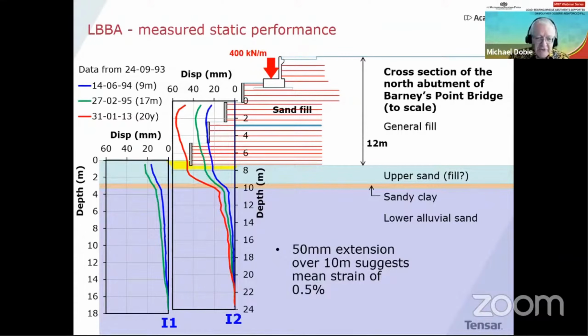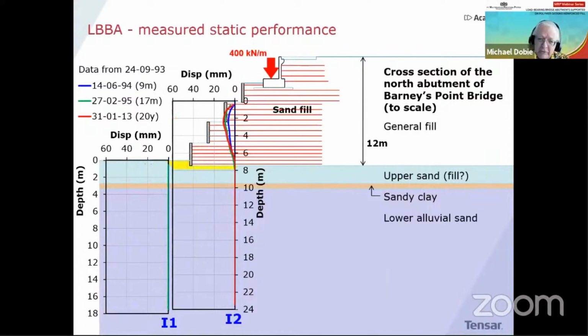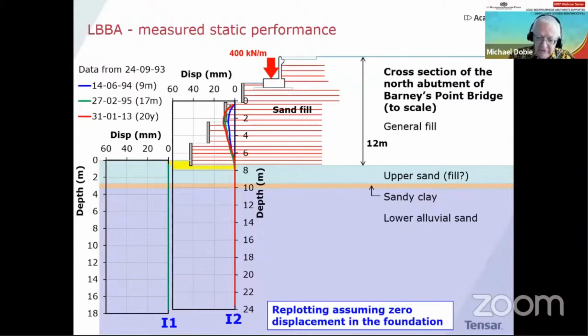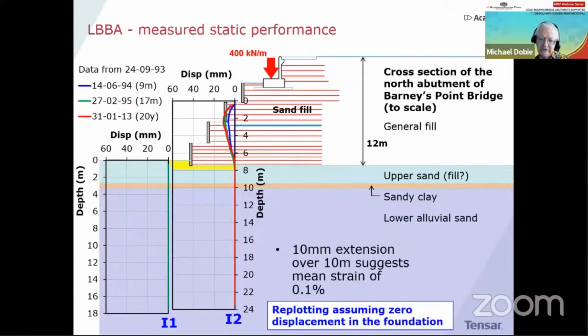However, in fact, the majority of that deformation has come from the foundation soil. So if I perhaps do something which is not a rigorous thing to do, but if I remove the effect of the foundation soils like this, and I assume that we only look at the movement within the reinforced soil block, then you can see that over that post-construction time period, the deformations are very small. So that's assuming zero displacement of the foundation. So if I go to my piece of Geogrid of 10 meters length, and I now look at the mean strain within the reinforced soil mass, it could be as low as 0.1%. So you can see that the performance of the structure is very much in line with the normal design requirements for such a load-bearing bridge abutment. So it's a very wonderful case study, is Barney's Point Bridge.